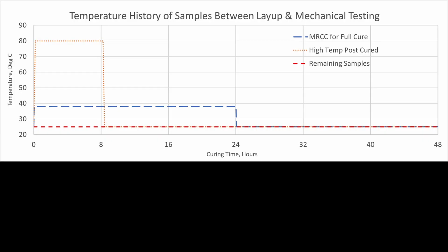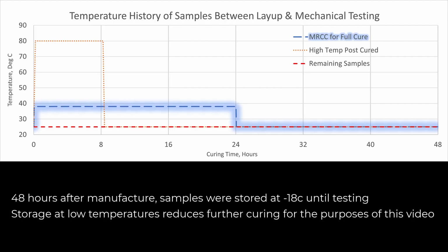One set of samples will be oven post-cured at 38 Celsius for 24 hours. These values were suggested by the resin manufacturer. A second set of samples will be post-cured at 80 degrees Celsius for 8 hours. These values are intended to show the effect of exceeding the recommended cure temperature on mechanical properties. The remaining samples were left at room temperature for 48 hours prior to testing.